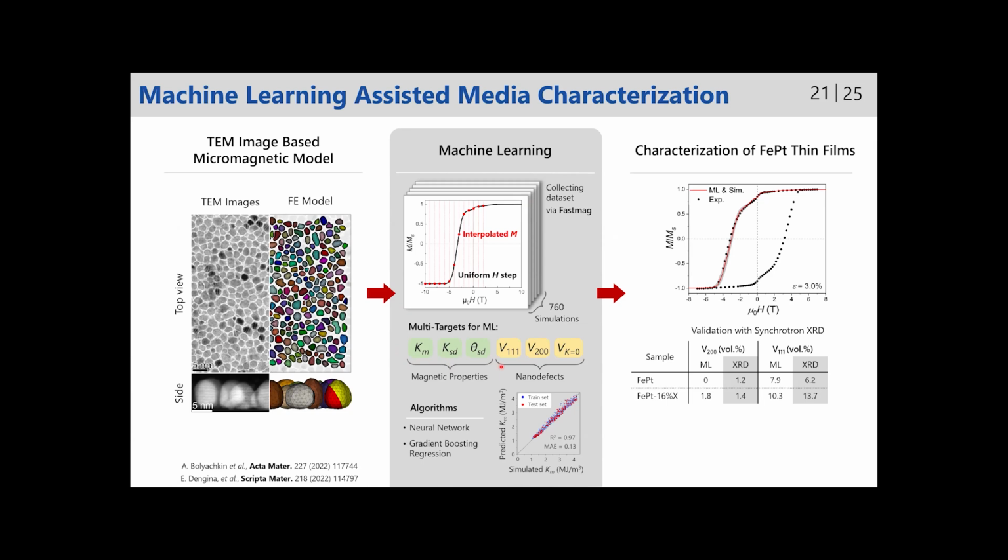For this, we trained neural networks, and the input data was just a sequence of magnetization points along the field range of interest. And when the neural networks were trained, you can see on the right that then as input data, instead of simulations, we used real experimental data. And for this experimental hysteresis loop, we have predictions for volume fraction of the defects. We can perform simulation based on these predictions and see that it's very close to what we have in experiment.